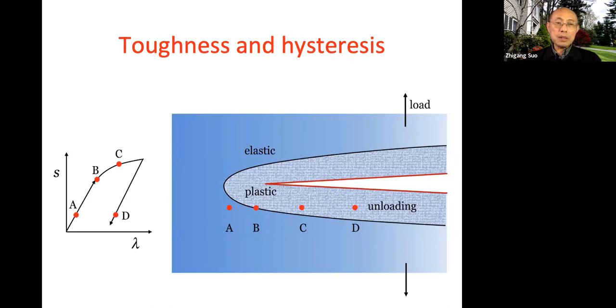So it doesn't have to be metal plasticity. Anytime you have a stress strain curve with this kind of hysteresis, you dissipate this amount of energy. So that's a point. Now, suppose you have a crack going through something like a metal or plastic, anything that has dissipation. What will happen is you apply a load, want to push this crack ahead. This crack not only needs to break atomic bonds, it also causes plasticity on a large scale, typically millimeter or 100 micron, very large compared to an atom.